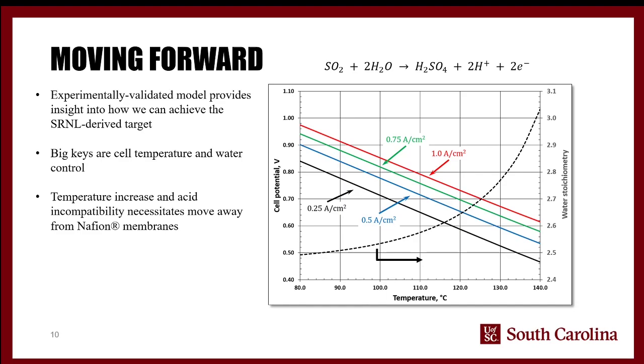The big key here is you have to pay attention to your water stoichiometry. So you have to pay attention to how much water is being fed with the sulfur dioxide. And what we find is that as the temperature increases, and in particular as you get above the boiling point of water, so when more water is entering the vapor phase, you actually have to feed more water in to achieve the current densities that you're trying to achieve and at the potentials that you want with the concentration of the acid that you want.